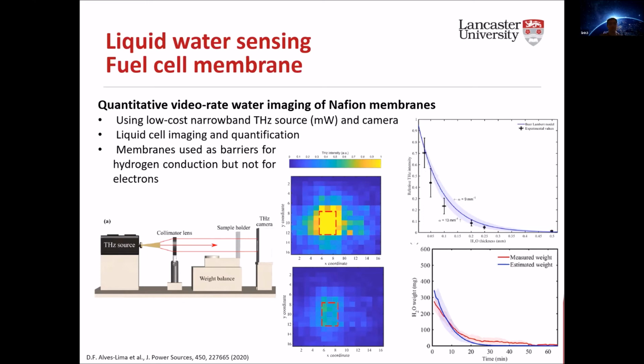And so we applied this to Nafion membranes, which, if you don't know, is a membrane that is commonly used in hydrogen-based fuel cells. We want to see the sort of water pickup there. With a Nafion membrane, we basically watched the water dry. From the relative transmission, we can estimate the water thickness, and from the water thickness, we can then estimate the water content. And this is benchmarked against a simultaneous gravimetric analysis, whereby generally there's a good agreement between the two.